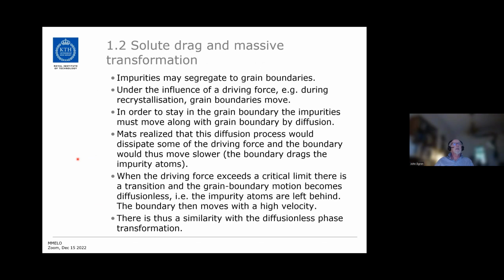Solute drag and massive transformation. Now, if you have a grain boundary, impurities may segregate to the grain boundary. And if there is a driving force, for example, during recrystallization, the grain boundary will move. But in order to stay in the grain boundary, those impurities have to diffuse inside the boundary with the moving boundary. And Mats, he realized that this diffusion process would need some of the driving force available. And then the motion of the grain boundary would be slower. So the boundary drags the impurity atoms.